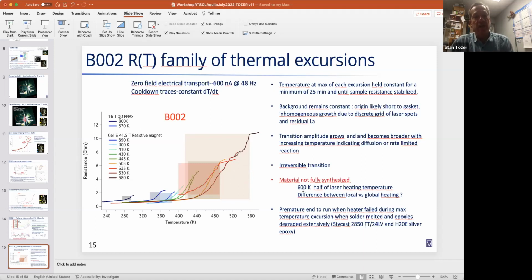But the interesting thing is that at about 600 Kelvin, which is the max that we went to, we're about half the temperature that is achieved when we were heating the sample locally with the laser. And that, I think, goes to the fact that we are releasing the hydrogen. And I have stacked the two final curves, the 530 and the 580, together here.